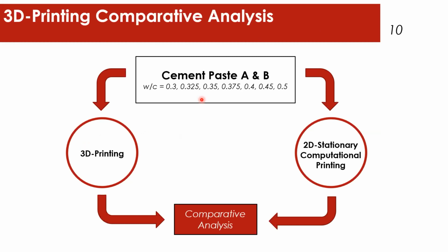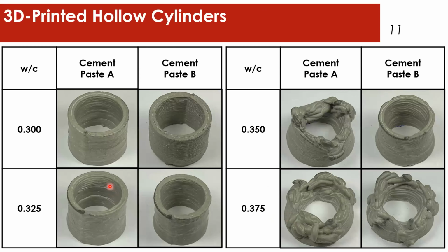So I prepared our paste, again both paste A and B, and I have actually printed an object that is a double wall hollow cylinder. And then on the other pathway, I'm doing 2D stationary computational printing, and then I'm going to bring them together for comparative analysis. So these are the actual objects that I printed, which are very small, on the order of 27 millimeters tall by 36 millimeters in diameter. I show a range of objects here from 0.3 to 0.375 water to cement ratio, some printed and some collapsed in between. If I go to a water to cement ratio as high as 0.4 to 0.5, the cement paste slumps completely and it won't print at all.